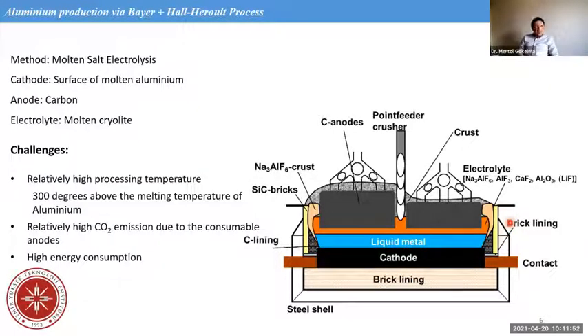Some important challenges: the temperature is relatively high. I call it high because it is 300 degrees above the melting point of aluminium. So actually to receive aluminium as a liquid product, we don't need much higher than 660 degrees Celsius. But the processing temperature of the molten salt electrolysis is 960-70 degrees Celsius. And the reason of this is the melting point of the electrolyte. The solid electrolyte would not pass the electric current. That's why we need liquid, and that's why we are a lot above the aluminium melting temperature. So this is one of the challenges I would define. And an electrolyte doing the same job as cryolite, but having a lower melting point would save a lot of energy and money.